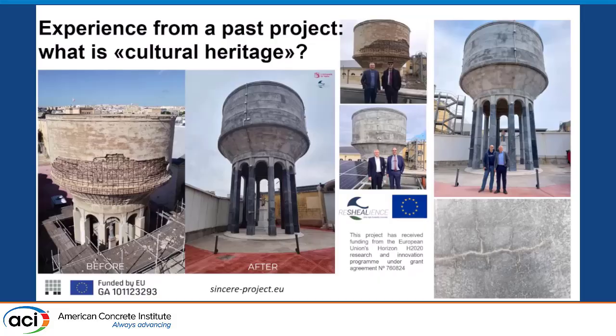And it was also an interesting educational lab. As a matter of fact, on the opposite side, one that we cannot see, the concrete was perfect, and the cores yielded 40 megapascal compressive strength, so you could say it was a very good concrete. And here, this corrosion was the effect of the erosion of the wind-driven sand, containing also chlorides, because here you form the turbulence. The sea is here, and the main wind direction is exactly here. So this is where you have the turbulence effect due to the wind. It's not the pressure effect.